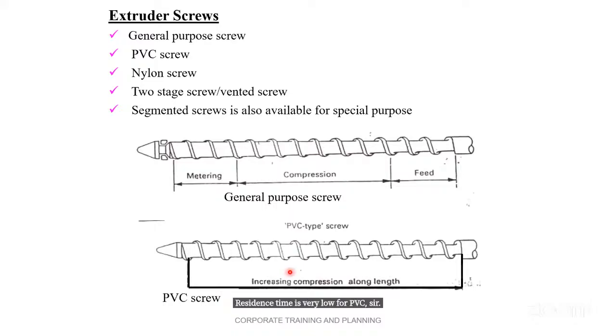Correct. 100% correct. Your answer is 100% correct. Because PVC is a very heat sensitive polymer. It starts to degrade immediately. If you take virgin PVC, virgin white powder PVC, it degrades. It doesn't have flow at all. It starts burning at 80 degrees temperature.